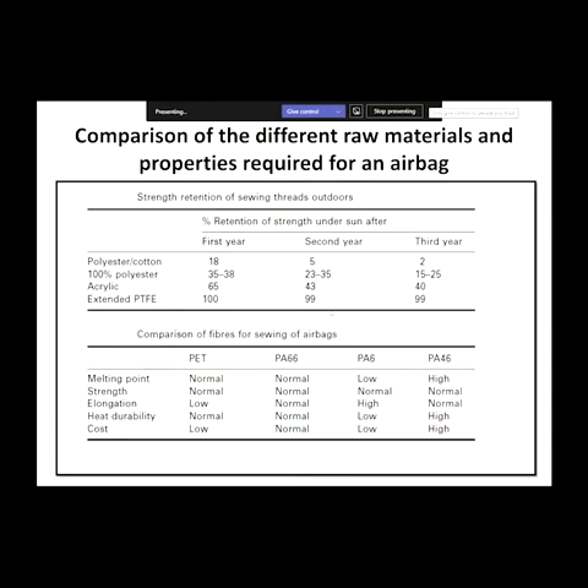You see, I already told you, for outdoor applications, you see the expanded PTFE thread, even at the end of the third year, it is losing only 1%. That means it has extremely high UV resistance. Compared to that, at the end of the third year, polyester cotton thread has lost almost 98%. Polyester thread has lost nearly 78 to 85%. Acrylic thread has lost 60% of strength, whereas the ePTFE is still strong.